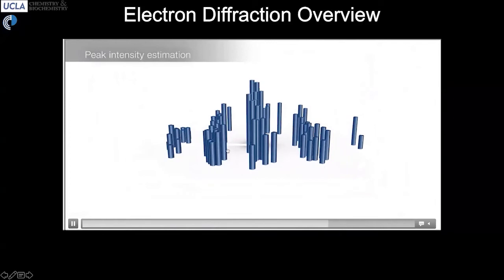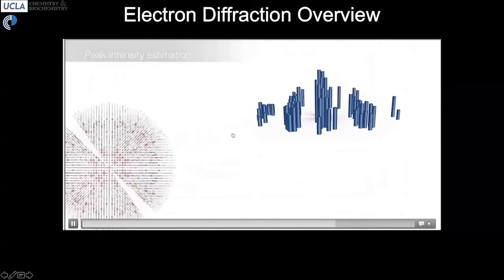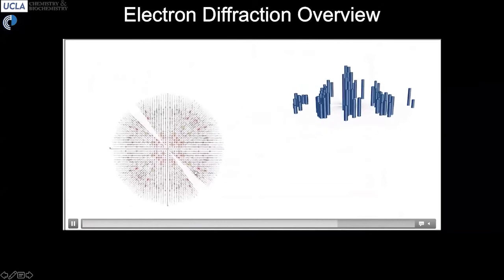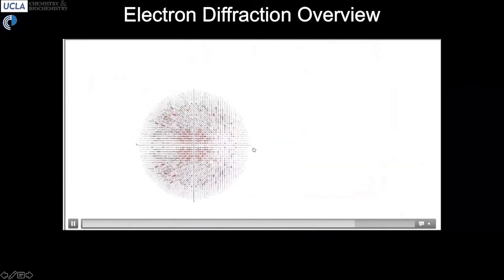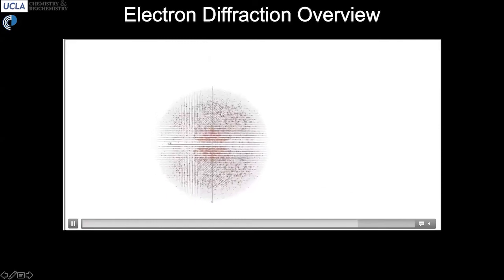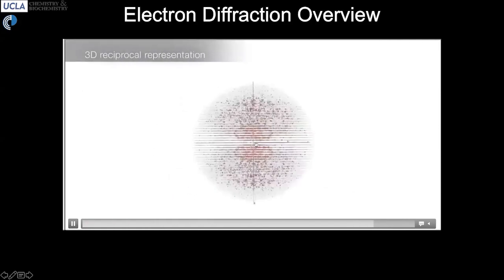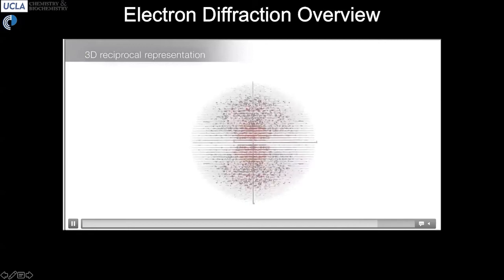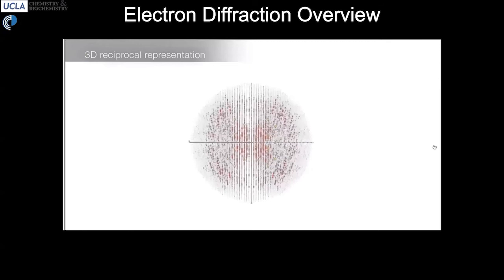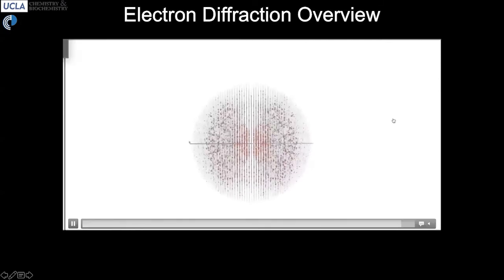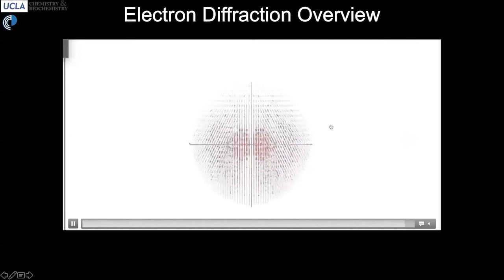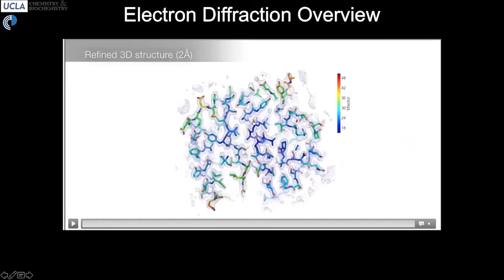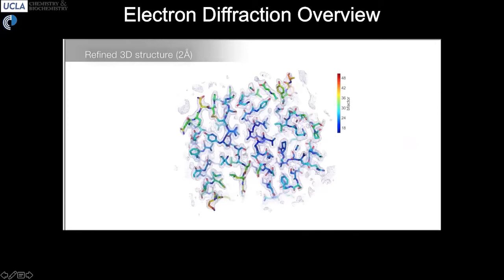And you can see all of these points of particular constructive interference are measured and assembled into this three-dimensional sphere of information. This three-dimensional information is then fed into reconstruction programs that have algorithms to try to invert this information and convert it into electrostatic potential, some continuous density that then represents your molecule. That continuous density is then fit using humans or algorithms to an atomic model. And so you fit an atomic model into this density and interpret the molecule that you are observing.